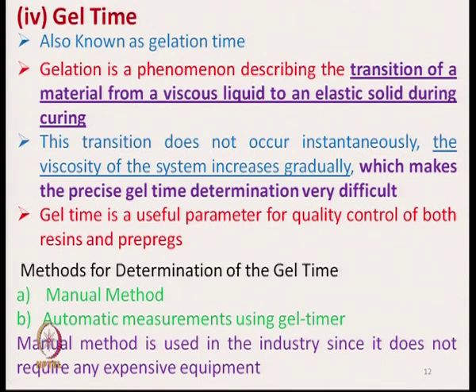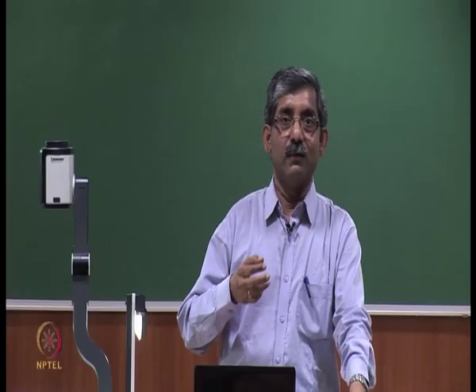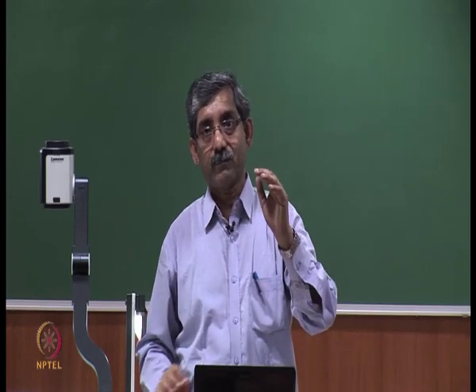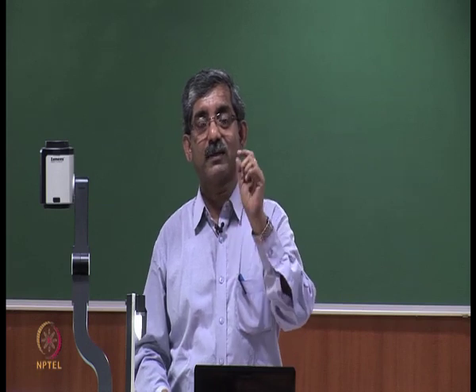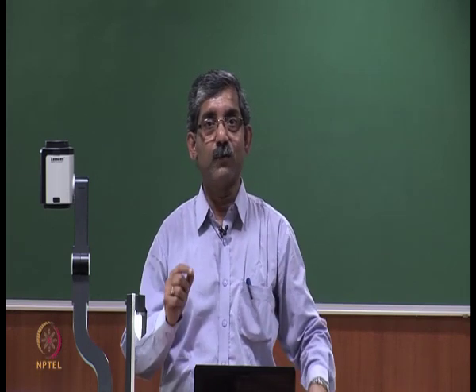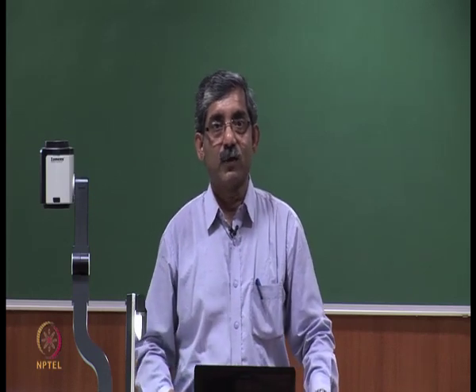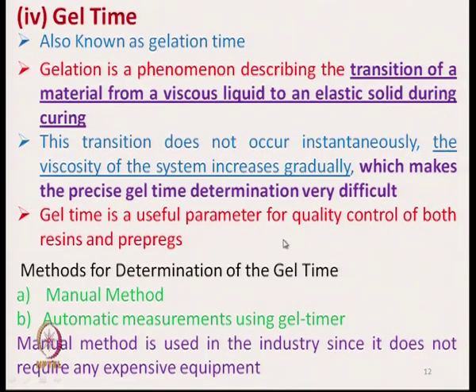It is very difficult to measure the gel time precisely because this is taking place gradually, it is not at a certain point. So, for precise measurement we have to do repeated tests manually. Gel time is a useful parameter for quality control of both resin and prepregs. We must know the gelation time so that we can know by what time the curing should take place. The methods of determination of the gel time are, one, a manual method and, second, automatic measurement using a gel timer.